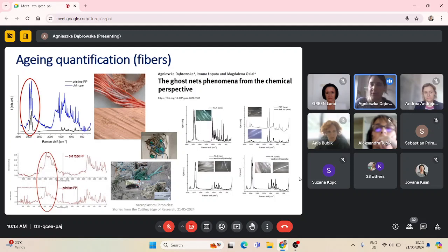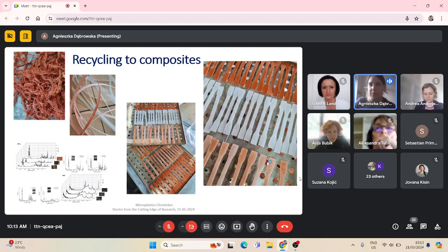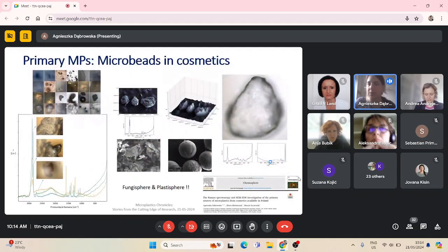This is relevant for several reasons, but one of them is a practical one, understanding better the aging of polypropylene in that case, and having a lot of research on ghost netting and fibers that are from the environment. We were able to propose the aging pattern, the structure modification on the interface, and we were able to recreate them in the new material, composing the pristine polypropylene and the polypropylene from ghost netting, so from the fishing gear that was lost or abandoned at sea. As you probably know, there is a huge problem with bycatch, with entanglement of biota, and presence, of course, of a possible source of microplastic, because the weathering fishing gear creates a lot of fibers during its aging. This is recycling, but also upcycling is possible.